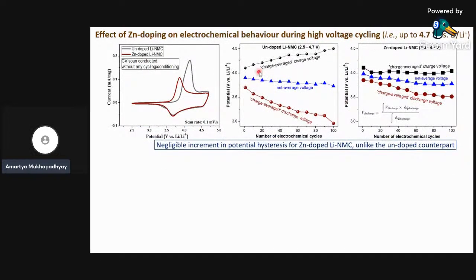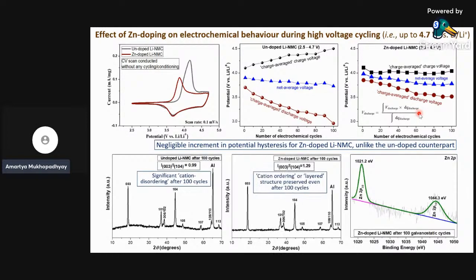Now, this is the undoped lithium NMC cycled up to 4.7 volts as the upper cutoff. One can see a continuous fade in the average voltage, which implies a change in the structure of the material, at least at the electrode, and at the same time a huge increase in the polarization between the charge and discharge voltage. But for the doped system, the increment in polarization is almost negligible in comparison. So this is a first indication that the structure was more stable when zinc was doped in lithium NMC.